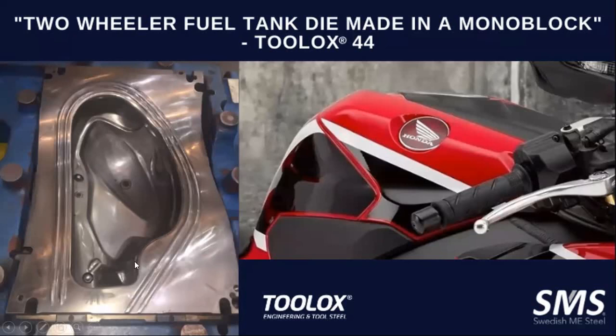Here, the previous solution which it replaced was casting plus chrome plating. For casting, every 80,000 to 1 lakh shots, you need to bring the die out to the nearest recoating center. So during the entire lifespan of that die, it comes out at least 10 to 15 times, and each time it is out of production for 2 weeks. With Toolox 44 plus nitriding, the last we heard was 5 lakh components without any issues. That's the benefit that the material can give you.